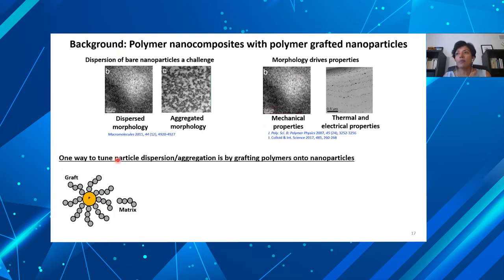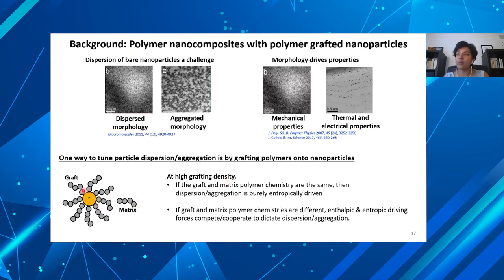So one way people have been tuning or controlling the particle dispersion aggregation is through grafting of polymers on particles. And so they can choose the chemistry of the polymer on the particle, and then basically by the design of these graft chemistries and matrix chemistries, they can tune where the particle goes, especially at high grafting density. So what I mean by that is, imagine this particle is completely densely grafted with polymers. You've essentially covered the particle surface and screened the particle-based interactions, and everything is really controlled by the polymers on it and how that interacts with the polymer around it, the matrix.